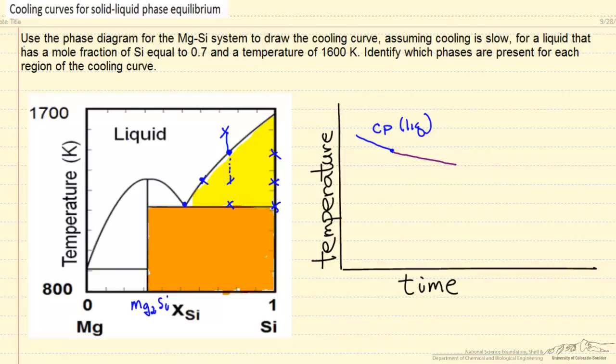Now we get to this point, we're looking at a slightly different situation. This is eutectic. As we continue to remove energy, we have a liquid at the eutectic composition in equilibrium with silicon. We're going to stay at constant temperature while we remove the rest of the energy.